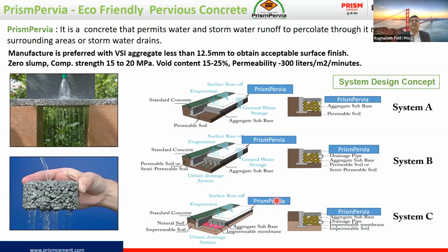penetrate underground soils. With this concrete we can achieve strength up to 15 to 20 MPa, and the voids we design for are 15 to 25%. The workability of concrete is zero slump, since there are no fines in this concrete. If you see the water permeability, it is 300 liters per square meter per minute. So in 1 square meter area per minute, the water permeability is very high, 300 liters, since the void ratio is very high.